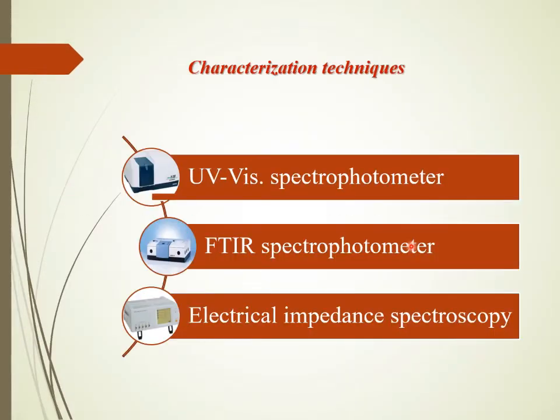Characterization techniques. An ultraviolet-visible spectrophotometer was used to determine the type of transition and the optical band gap energies of the prepared solid polymer electrolyte materials, and the measurement was performed at the Spectroscopy Department, NRC. Meanwhile, to confirm that a strong interaction occurred between CMC and PEO, and to determine the functional groups of the individual polymers, an FTIR spectrophotometer was used. Also, AC conductivity, activation energy, and some dielectric properties were determined in the range from 15 Hz to 1 MHz at different temperatures via electrical impedance spectroscopy.